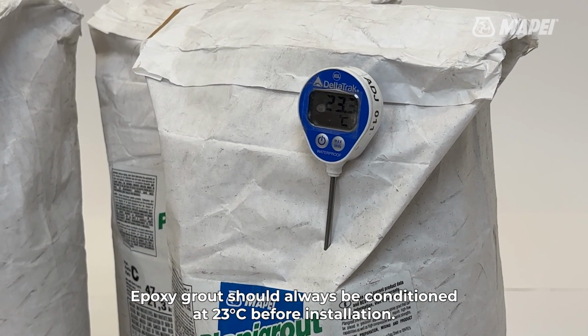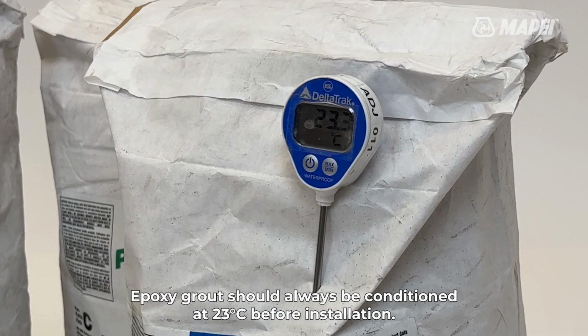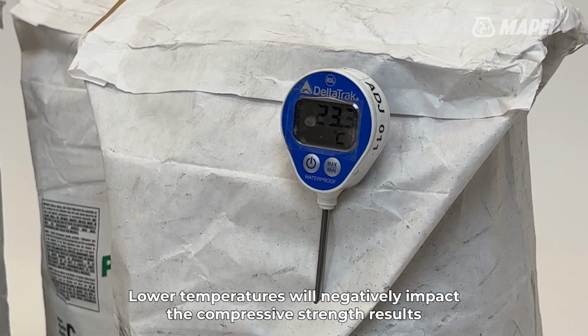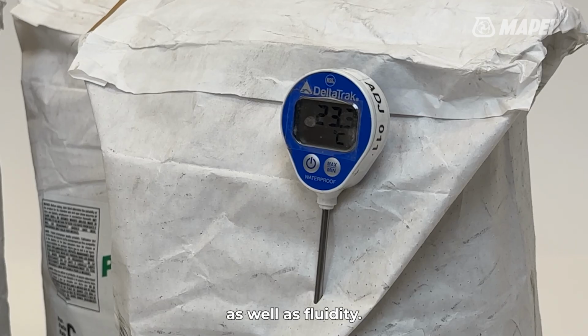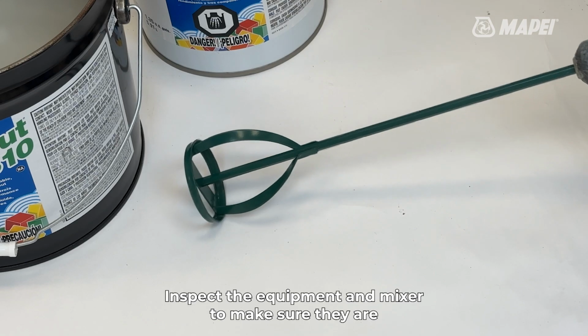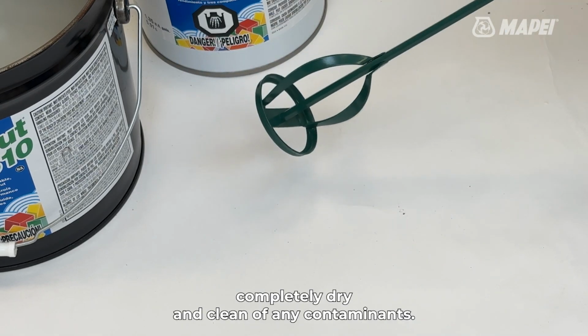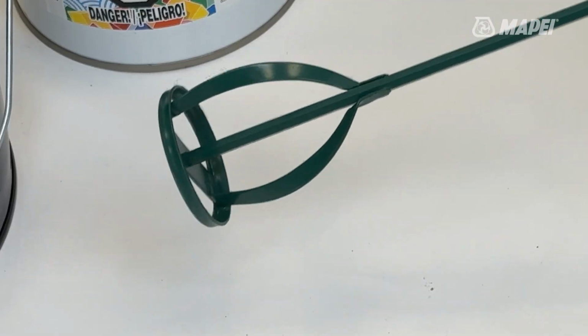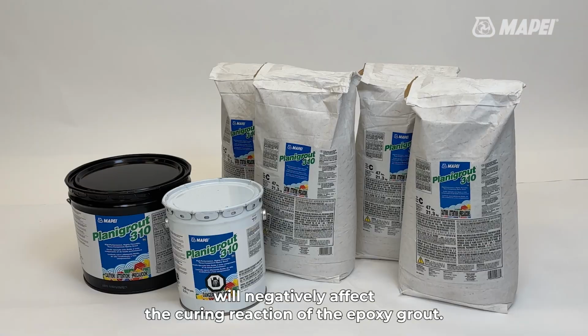Epoxy grout should always be conditioned at 23 degrees Celsius before installation. Lower temperatures will negatively impact the compressive strength results as well as fluidity. Inspect the equipment and mixer to make sure they are completely dry and clean of any contaminants. Any water contamination will negatively affect the curing reaction of the epoxy grout.